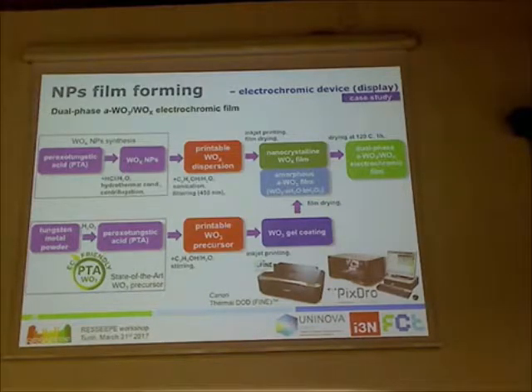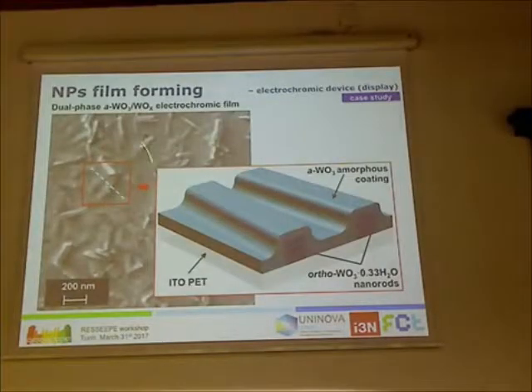You can combine both: you spray the particles and then spray the amorphous phase, creating what we call a dual phase layer. So we have a mixture of amorphous and crystalline, and this is the resulting film.